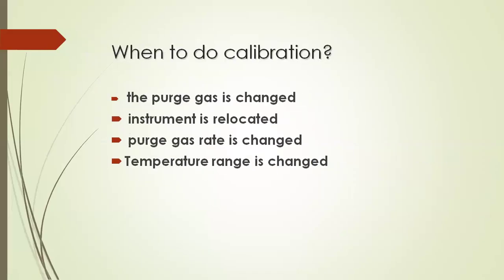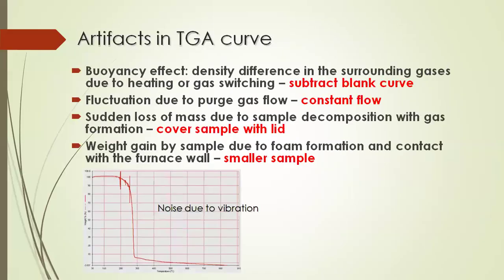You should do the calibration of the instrument when the purge gas is changed, when the instrument is relocated, when the purge gas rate is changed, and when the temperature range is changed. Most important for students, you should be able to identify the artifacts in the TGA curve. You should not interpret these as TGA events. There are many effects like the buoyancy effect, where there is a density difference in the surrounding gases due to heating or gas switching. If there is a buoyancy effect, then always subtract a blank curve from your original curve.